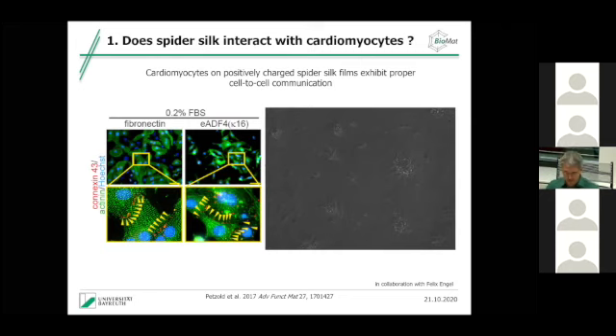So therefore, we actually investigated silk, because as mentioned before, we can do with silks whatever. We can even 3D print that. So the main question here was, do cardiomyocytes interact with silk surfaces? And to make a long story short, again, with our regular silk, they don't. Remember, no cell would like to attach to the silk. So therefore, we had to further engineer our silks. And what we did, we introduced positively charged amino acids. So on purpose, we changed the surface charge of the silk, which is typically negative, into a positively charged surface. The rest was the same.